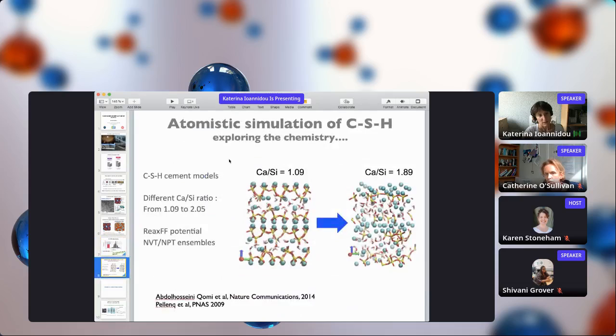As I was saying, there is a lot of work done from atomistic simulations trying to understand this structure. Here, for example, you see how this material looks when we are at the tobermorite limit, with crystalline layers of calcium and silicates with water and calcium ions in between. But what is actually mostly observed in the cement we are using is a much more amorphous and messy structure, with a much higher calcium over silica ratio.